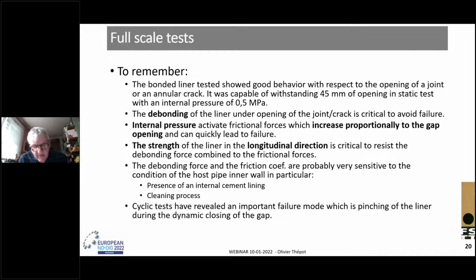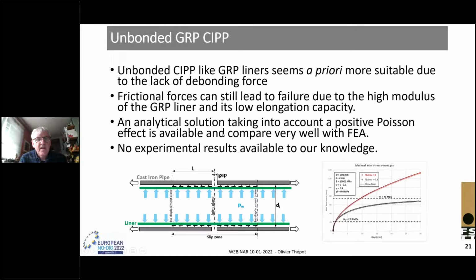Cyclic tests have revealed an important failure mode, which is pinching of the liner during the dynamic closing of the gap. Considering the experimental results on bonded liner, it seems that unbonded CIPP like GRP liners should be more suitable due to the lack of debonding force and also a lower frictional coefficient.